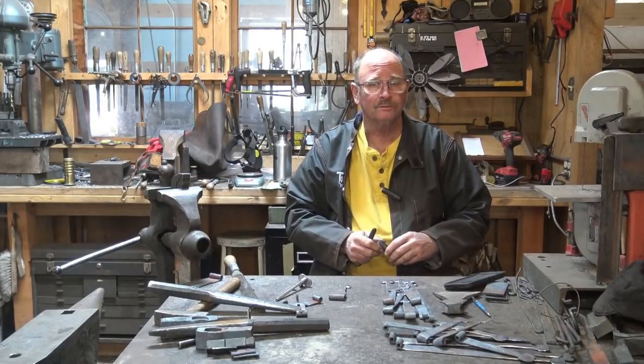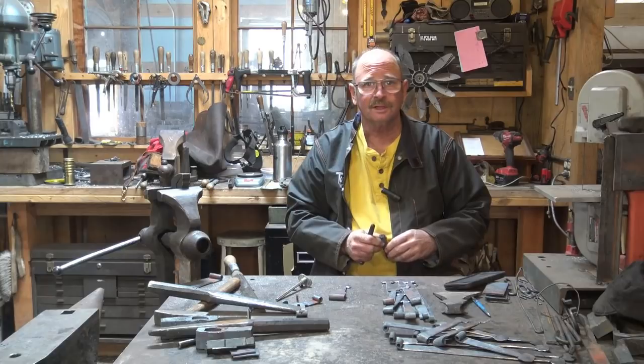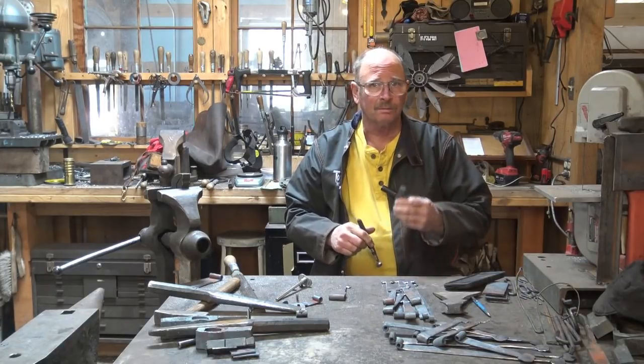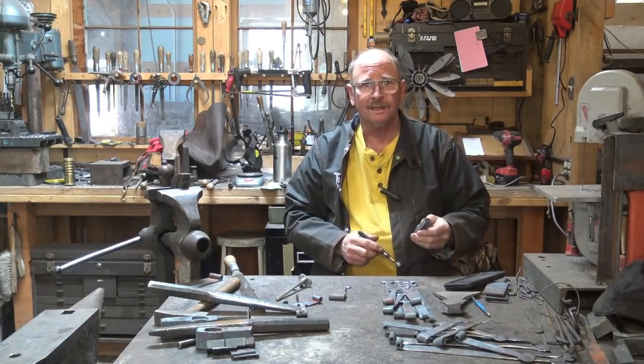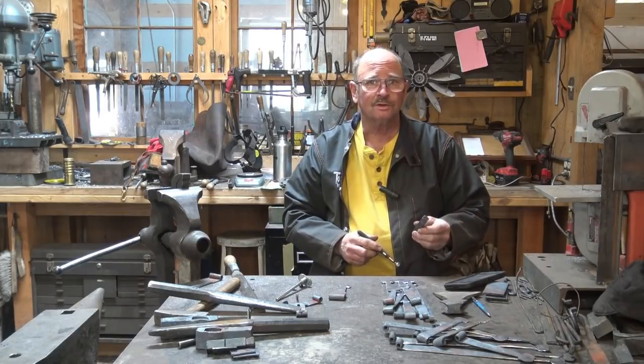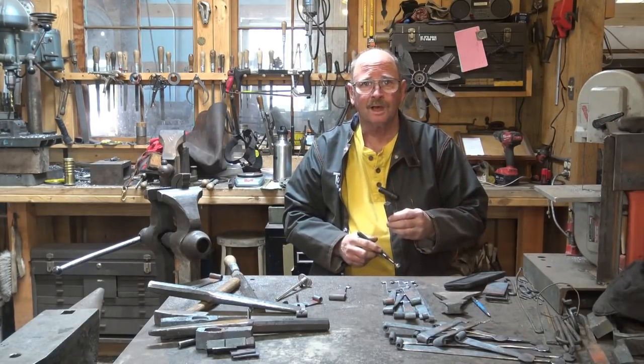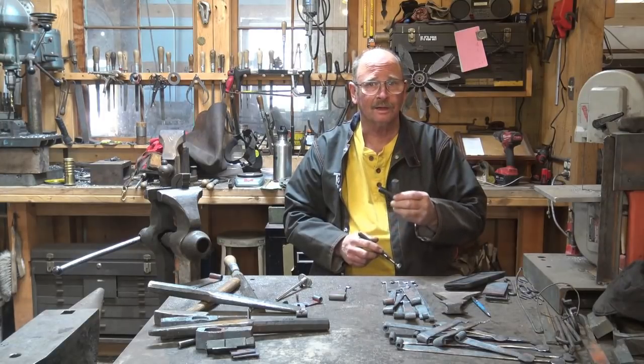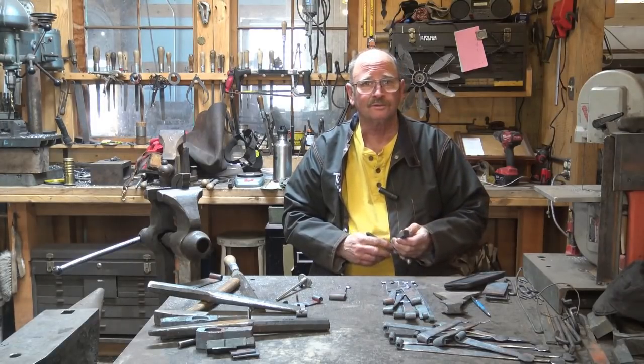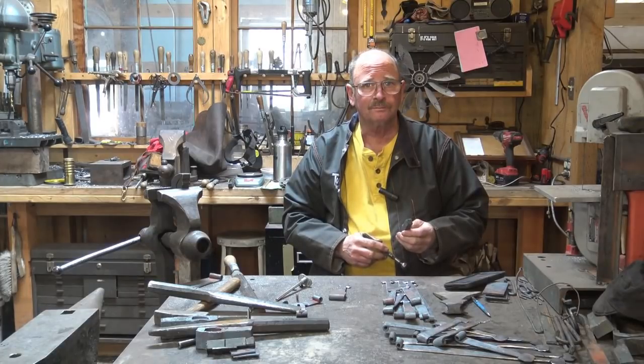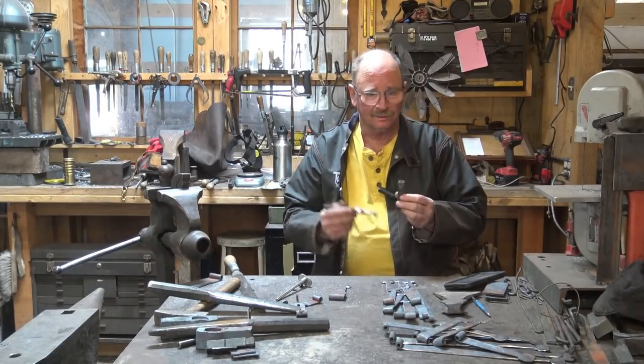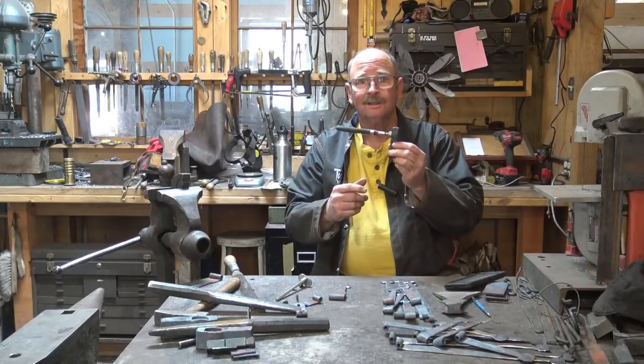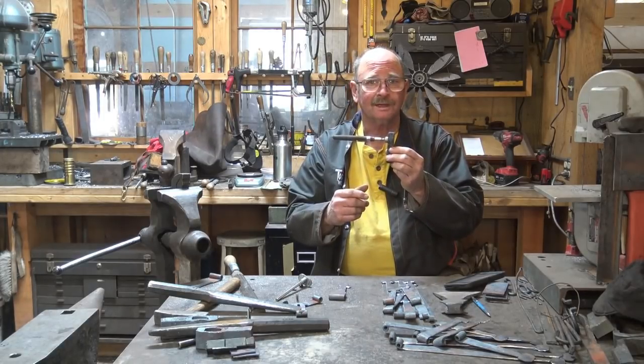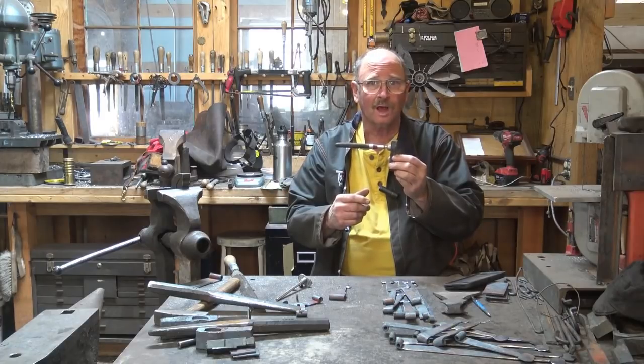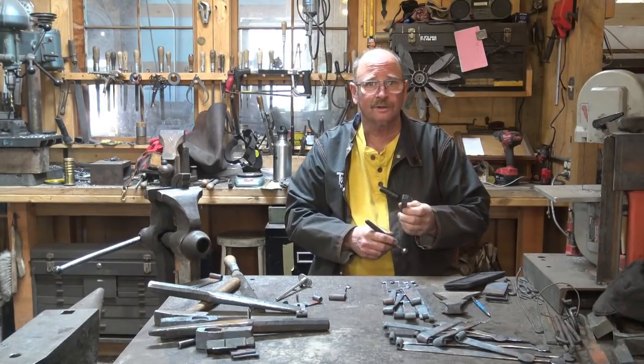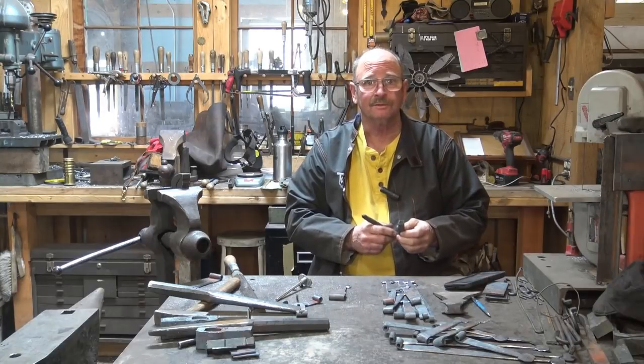I think it's probably true for simple steels like the 1085s, the 1095s, and probably even W1, which is what I happen to have in my hand here. But I'm not sure that it still holds true when you get up to the higher tech steels that need higher and higher critical temperatures. I suspect that most of those steels lose their magnetism and the magnet will no longer stick at about the same temperature, even though they need a critical temperature that might be 300 degrees hotter. And 300 degrees in hardening and tempering is a big temperature difference.